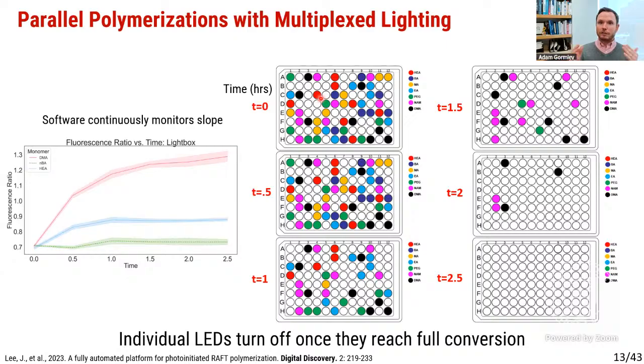What we ideally want is a system whereby each reaction is getting the right amount of light, the right intensity for the right amount of time. And so what we did here is we built this multiplexed array of LEDs. What you see here on the top left at t equals 0, everywhere you see a color is a polymerization mixture. Not all of the wells have polymers, only where you see color. We then initiate the reaction, and the robotic arm is picking up the samples and moving them into the UV-Vis every 10 minutes. It then measures the conversion by fluorescence and puts it back.